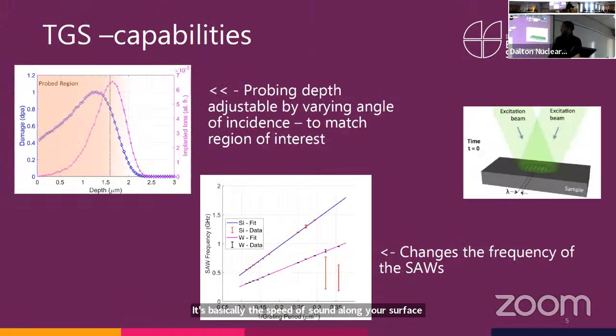And by changing this angle of incidence, you can change the spacing of this diffraction pattern, this interference pattern, which would then change the spacing of the diffraction grating. So if you had a wider grating, then it would probe deeper into your sample. So you are able to adjust the angle of your beams, and by that you adjust how deep into your sample you're probing.